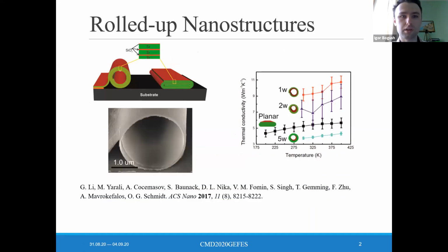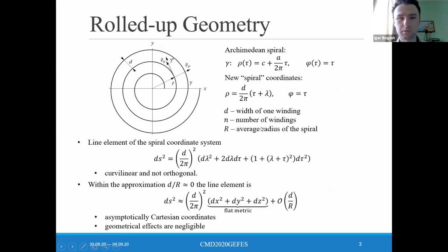We are studying rolled up nanostructures. They are thin silicon membranes covered by oxide film, and they can have a different number of windings. And experimentally, it was found that the larger the number of windings, the lower the thermal conductivity is. For example, for one winding, we have circa 9 watts per Kelvin meter, and for 5 windings, we have around 3.5 watts per Kelvin meter.